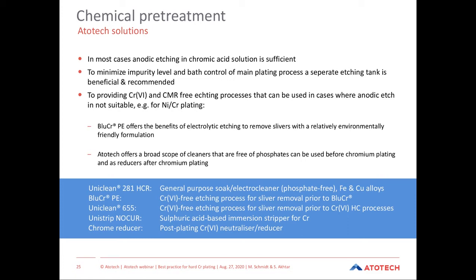We have several cleaners, which should usually be phosphate-free, for different alloys, for copper and steel. And to complete our portfolio, there are also several solutions for chrome removal, like the Unistrip NOCUR, or like chrome reducers or neutralizers to remove the residues of chrome 6 from the final plated parts.